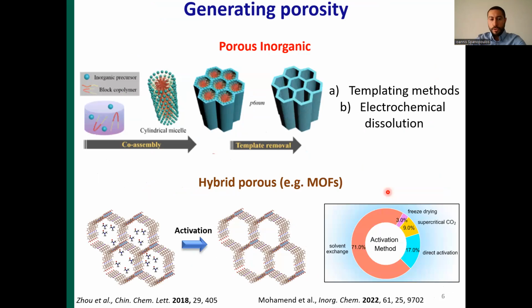So then, how is it possible to achieve porosity in general? In the case of the porous inorganic semiconductors, like porous silicon and porous germanium, there are different types of methods that can be utilized. One of them is the templating methods, using a soft or hard template, or electrochemical dissolution methods. In the first case, when the template is removed, the corresponding structure is rendered porous. In the second case, the electrochemical dissolution usually involves partial dissolution etching of the material, and this of course also gives rise to a specific porous network.